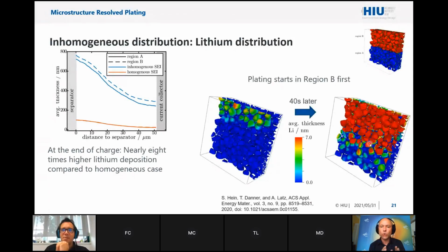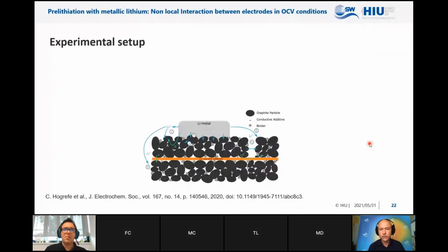But if we just have a small hole with a smaller SEI, the current is redirected to this region such that the current density is increasing so much that the corresponding overpotential is producing the plating in the part with the smaller SEI. So the message here is that you really have to consider the structural configuration to see at which points you get the plating and when the plating is going to start, and how, due to the production of plating, the currents are redirected in the electrode such that you might get earlier in some parts plating compared to the situation which would be completely homogeneous. So it's a very complicated situation, it's very subtle, but it's going to be more interesting.